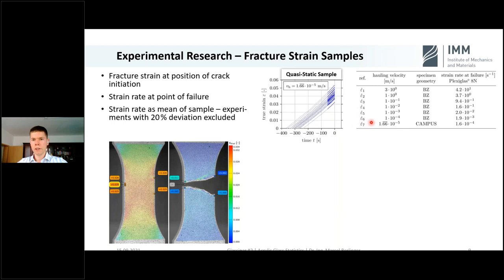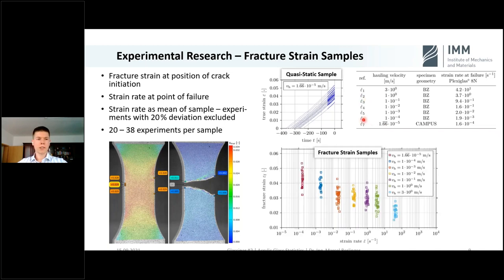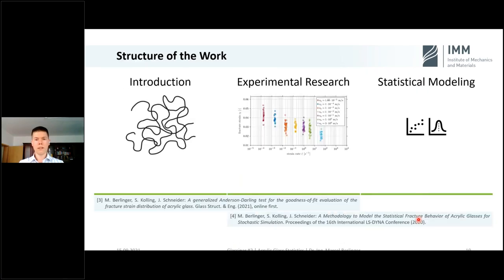From now on, I will talk not anymore of falling velocities, but of strain rates, here 1 to 7. And such we gained samples with 20 to 38 experiments per sample. Now all the 7 samples plotted in one diagram over the strain rate. We see that picture here. And that nicely shows the effect we are dealing with. With increasing strain rate, we're going to the right, the level of our fracture strain reduces, and the dispersion also drops. And these are the effects that I want to model in the following.